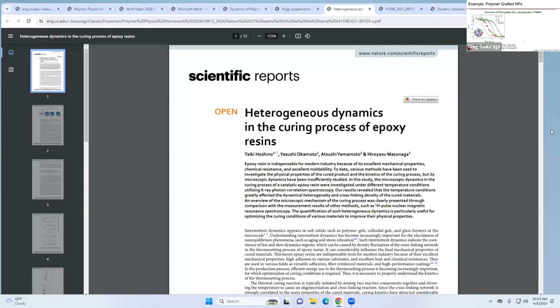But essentially what they saw is a collection of these correlation functions, where as you change the molecular weight, the time scale or the diffusion behavior of those particles is going to change in that matrix. That makes sense, right? We make our polymer more entangled, a thicker network, those particles are going to move around a lot differently, right? But this is a quantitative technique, a way to actually calculate that. These things are a couple nanometers. You can't see that. You can't do microscopy. You have to go in and use X-rays to figure that out, right?